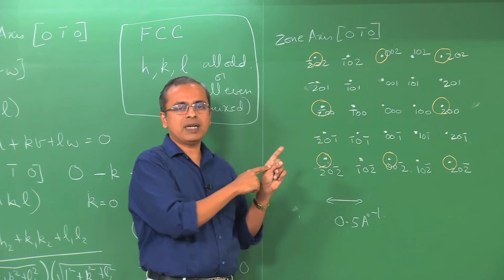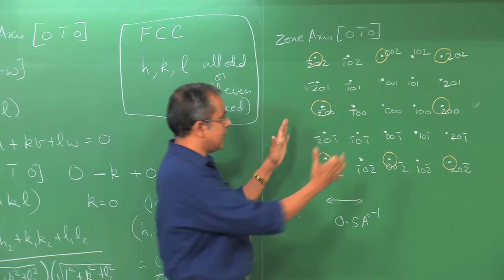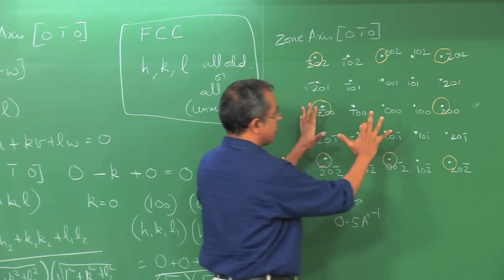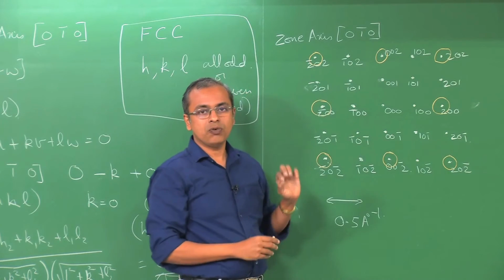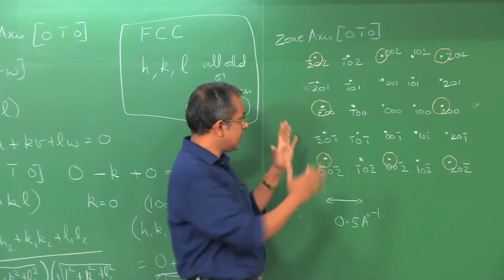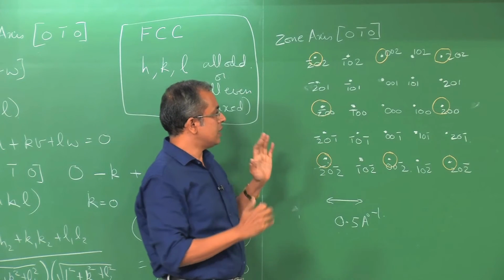That is like any other magnifying or decreasing of the magnification. In the context of a diffraction pattern, we talk of it as camera length. You can change the camera length, and that changes the extent to which these points spread out or come closer together, but the angular layout of points would be exactly the same, and the pattern that you would see would look exactly the same. So, this is how it relates.